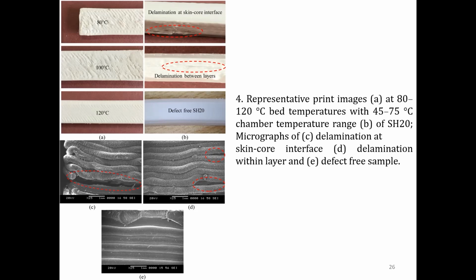Now, the perfect bonding, uniform texture, and good quality sample without any defects, we could observe when the bed and chamber temperatures are maintained at 120 degrees and 75 degrees C, as you can see in Figure 4A. Please do remember, these numbers do change when you keep the matrix material the same but change the reinforcement. So you need to tweak when you go on an exploratory mode.